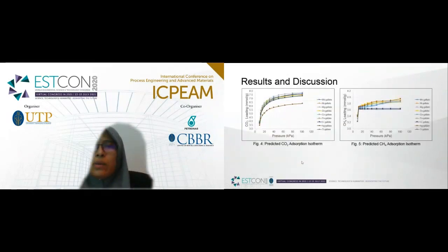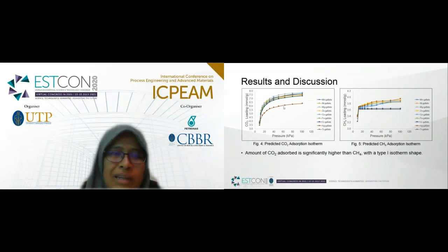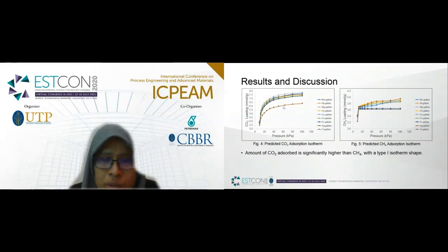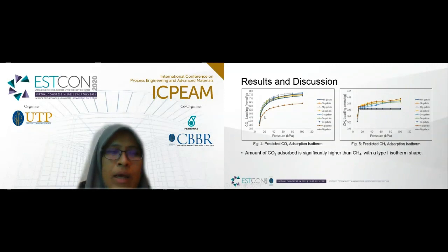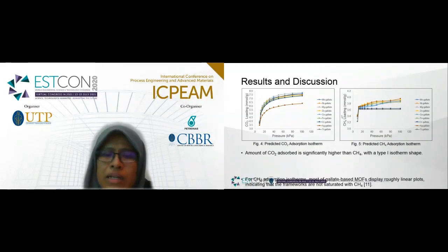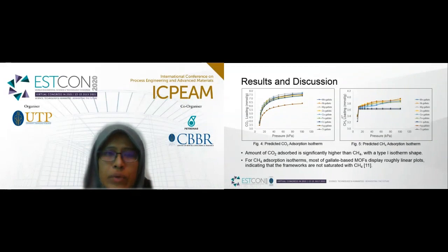For results and discussion, I will present the predicted single component adsorption isotherm first. As we can see, the amount of CO2 adsorbed increases as the pressure increases for all the gallate-based MOFs, and the amount of CO2 adsorbed is significantly higher than CH4 with a type 1 isotherm shape. At the initial phase of adsorption, CO2 molecules are in contact with the gallate-based MOFs surface and form a monolayer gradually. A steep CO2 loading can be detected at the low pressure range. For the CH4 adsorption isotherm, most of the gallate-based MOFs display roughly linear plots, indicating that the frameworks are not saturated with CH4 at this operational condition. Therefore, these are potential adsorbents for CO2/CH4 separation.